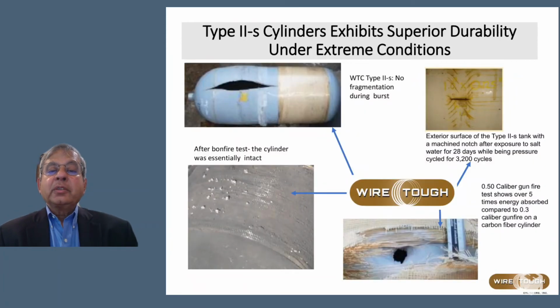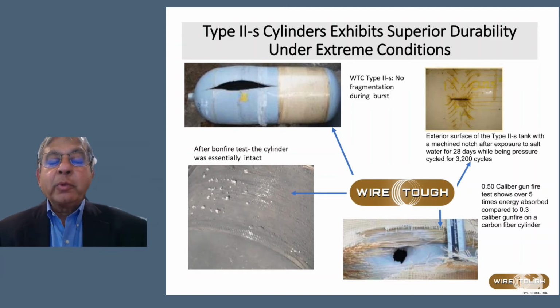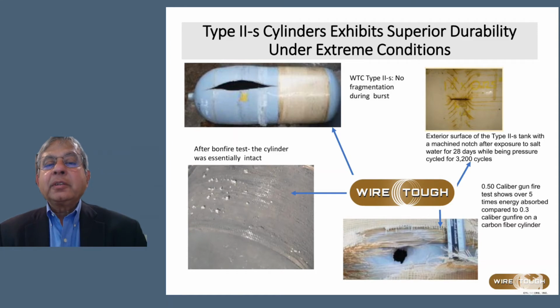Now these are some test results on Type 2S vessels. These are not vessels that are being designed for hydrogen, they're more for CNG and have a much thinner gauge liner as such. And as you can see, if you subject it to a burst test, you get a very graceful failure mode, which is a leak-before-break type failure. Then at the bottom left corner, you have the vessel after it has been subjected to a bonfire test, and you can see that the integrity of the vessel, the liner, and the other structural part, which is the steel wrap, are essentially intact.